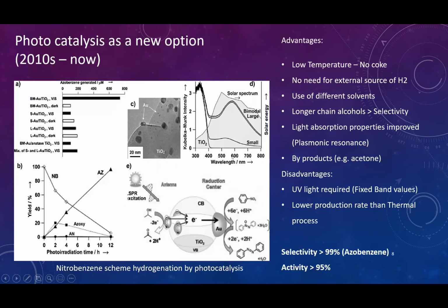Then lately, in the last years, the development of photocatalysts has led to low temperature reactions. So, no coke, no need for an external source of hydrogen, and use of different solvents. When we have longer chain alcohols, at least like isopropanol, we have higher selectivity. We can improve the light absorption properties with nanoparticles, with fewer byproducts or byproducts that are added value. The disadvantages: UV light required and lower production than thermal processes, but high selectivity, at least 99% for azoxybenzene in this case.